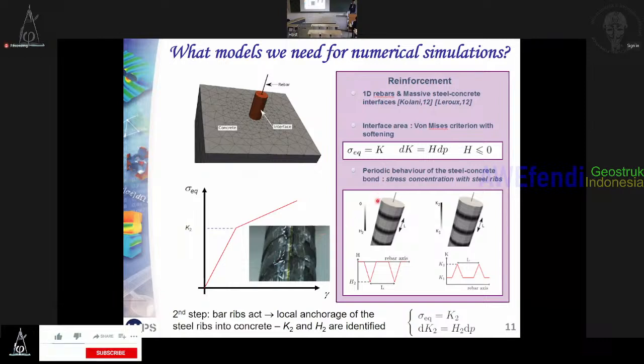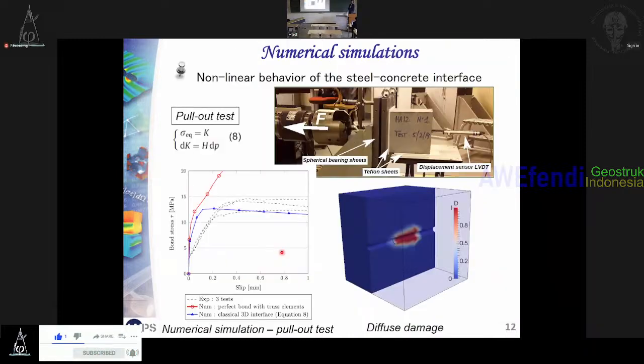So the idea is to modify some parameters, for instance the plastic strength here, and also the yielding here, depending on whether you are at the top or the bottom of the ribs. To show you what type of result we can have, here you have the classical pull-out test. The only difference is that when you do numerical simulation, as I said, you have to master the boundary conditions. Here we put a Teflon in order to minimize friction between concrete and steel. So it's easier to model.